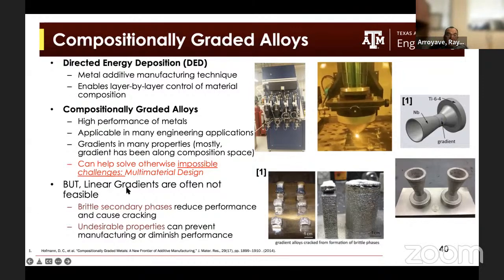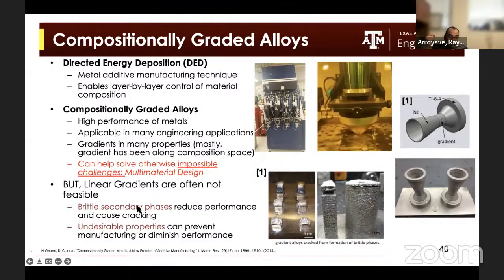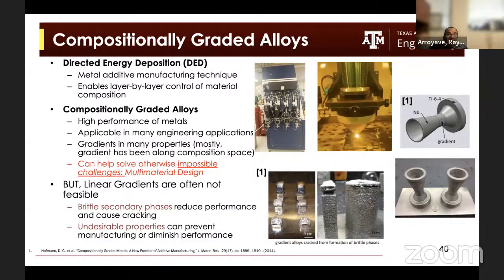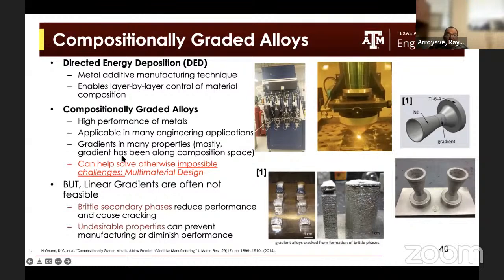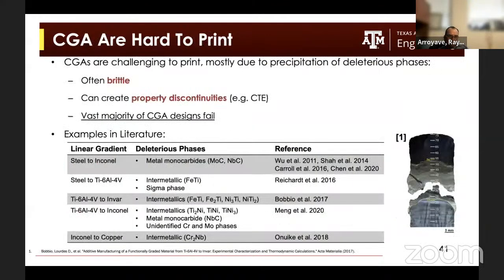Unfortunately, when you try to do this compositional grading with linear gradients that just connect one start composition to an end composition, it turns out that undesirable phases appear, and oftentimes linear gradients lead to undesirable properties that can compromise the manufacturing of the part and diminish its performance. So it turns out that compositionally graded alloys are challenging to print.